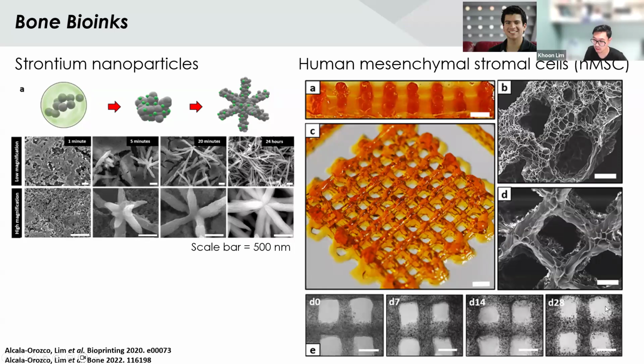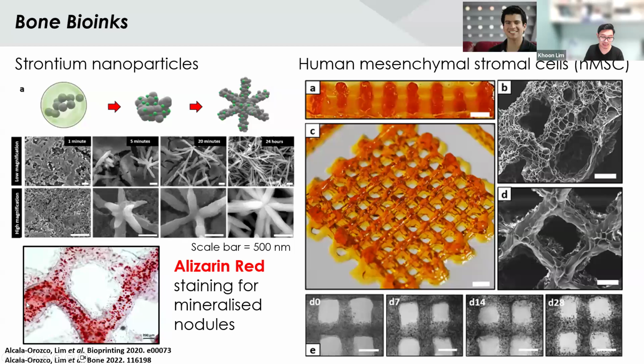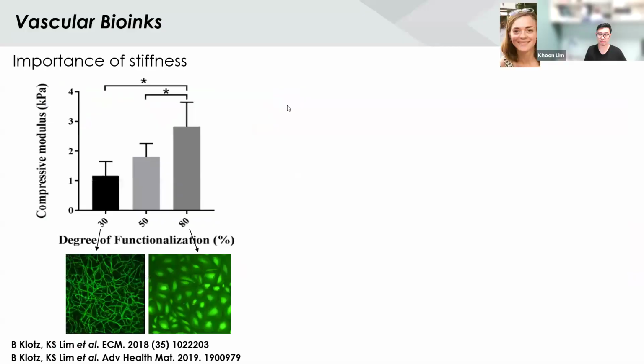What I'll draw your attention to is this bottom panel here, where you can see from day 0 up to day 28, there are a lot more darker dots that are forming on them. And all of these dots are when the MSCs themselves are starting to mineralize. So we stain for calcium deposits within them, and you can see the cells are within the fiber, and within the fiber, they are starting to form all of these mineralized nodules. So the presence of the strontium is there to support the cells to start making bone in this material.